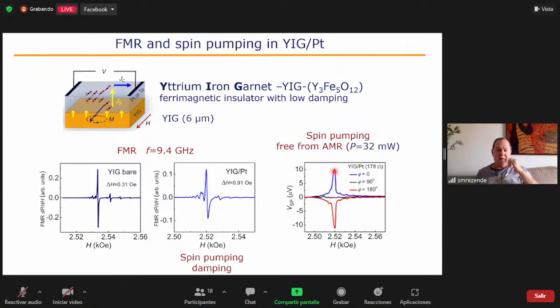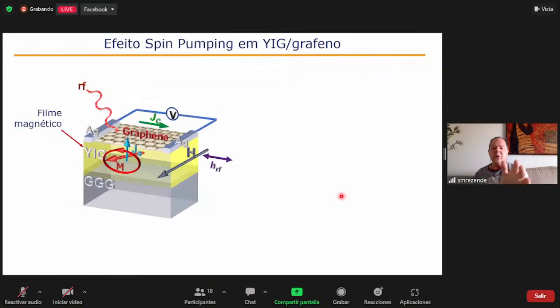This has several microvolts of intensity, and if we have the magnetic field in this direction, we have a positive peak. If we reverse the magnetic field, we reverse the polarization, and then the cross product of sigma with JS inverts sign, and the peak becomes negative. And if the magnetic field is perpendicular, there is no voltage because the cross product vanishes. So we use YIG to make this experiment with graphene.